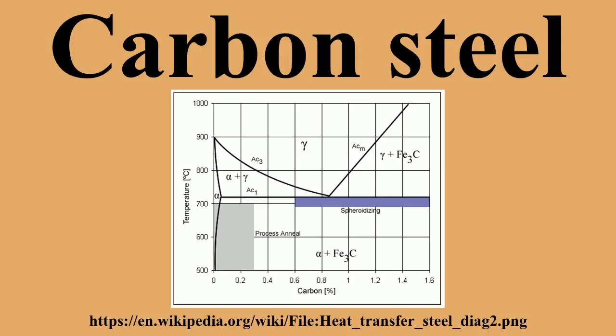Process annealing. A process used to relieve stress in a cold-worked carbon steel with less than 0.3 Wt% C. The steel is usually heated up to 550 to 650 degrees Celsius for 1 hour, but sometimes temperatures as high as 700 degrees Celsius. The image rightward shows the area where process annealing occurs.